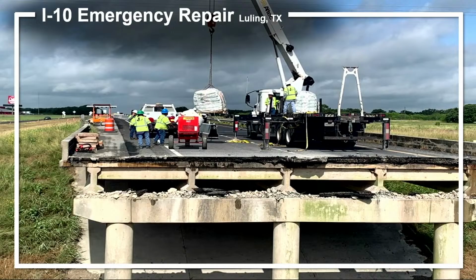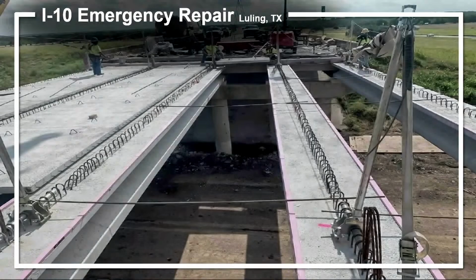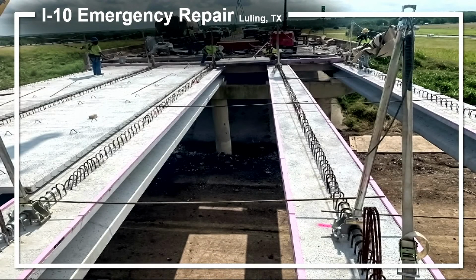This was the I-10 emergency repair in Texas. An oversized big rig took out an overpass. Well, they needed to get strength fast to repair it. They had to repair 10 pillars and get strength on those pedestals before installing the crossbeams. TxDOT said you have 24 hours to get the crossbeams on. So they used Rapidset concrete mix, our very fast-setting concrete, to repair those pillars, and they were able to open that up because of the very fast strength of the Rapidset concrete mix.